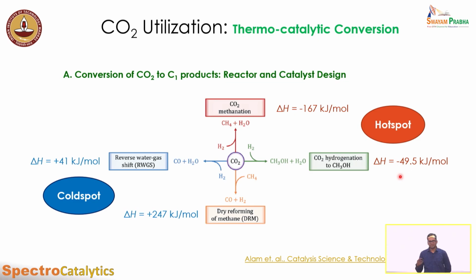Exothermic reactions generate huge amounts of heat during the reaction, and if that heat is not dissipated properly, it increases the temperature of the catalyst bed and hot spots form. Because of these hot spots, we see structural modification of the catalyst, which detrimentally hampers overall activity—we can see sintering of the active particles and so on.